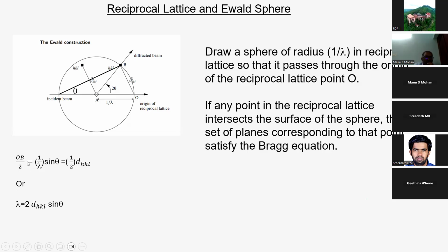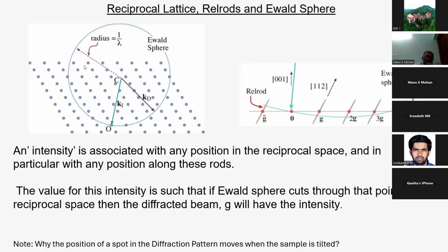Now you can have a geometrical construction here. You extend it. If you take OB by 2, you can write, using the angle in a semicircle is 90 degrees, OB by 2 is 1 by lambda sine theta. If you expand it, lambda equals 2d sine theta. So Bragg's law is proved from the Ewald sphere also. Assuming that OB is a reciprocal lattice point that gives reflection, the OB vector satisfies Bragg's law. Therefore, wherever the Ewald sphere cuts through the reciprocal lattice, you get a reflection. So that's what is drawn here.